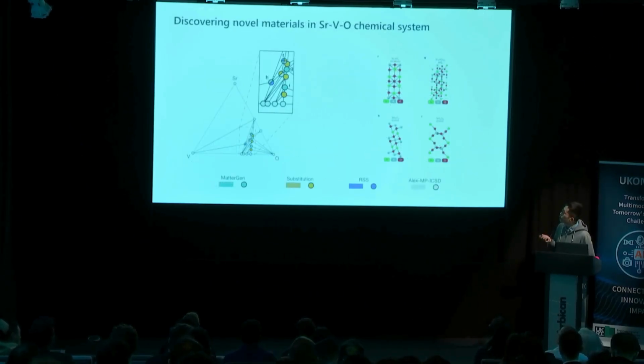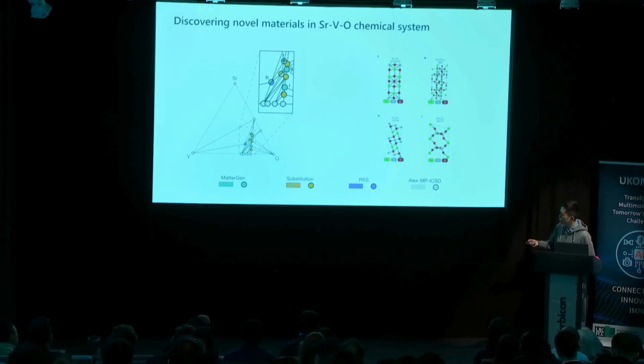So this is one example of one of those fine-tuned models. Here we are using it to discover novel materials in a specific chemical system called the strontium-vanadium-oxygen chemical system. You can see that MatterGen generates a lot of novel materials. We benchmark against some other methods in the domain, called substitution and RSS. It shows that it is better than RSS. It's similar to substitution, which is one of the very well-known methods people use to discover novel materials.